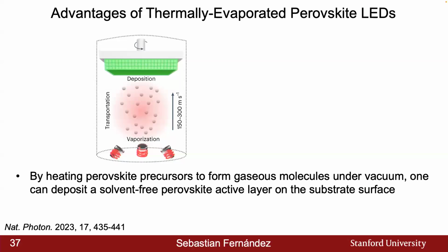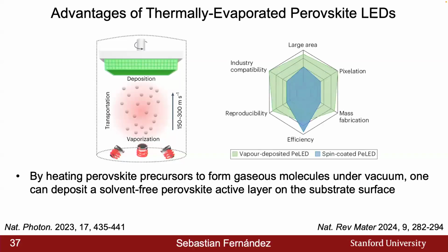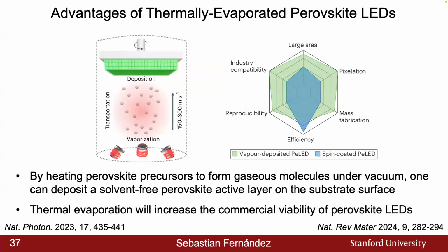And so why has there been such a key push within spin coating, within perovskite LEDs and perovskite PV in general as well? Actually, it can be explained quite succinctly with this chart here, in which, unfortunately, we just don't have the amount of tricks that we can do within thermal evaporation that we can do within spin-coated perovskites, such as those related to additives and crystallization. But given the other pros here related to industry compatibility, device areas, and reproducibility, I do believe that this is likely the path forward if we really want to commercialize these technologies further.